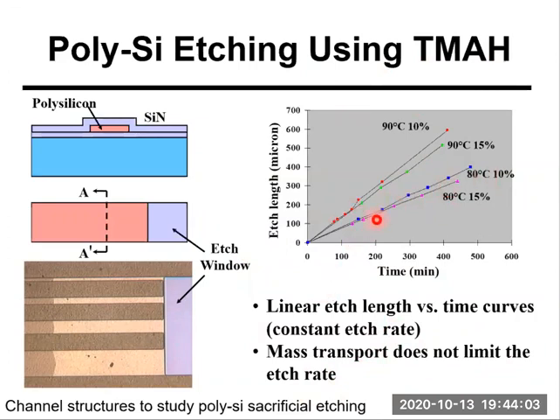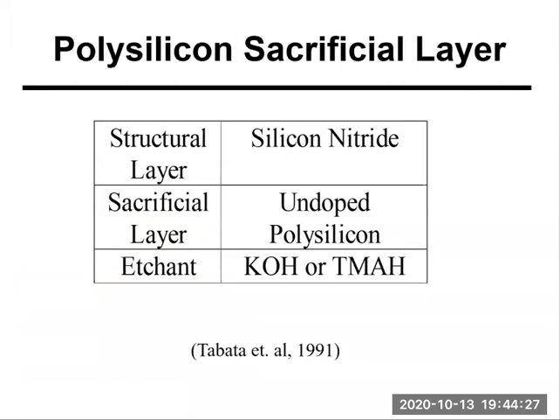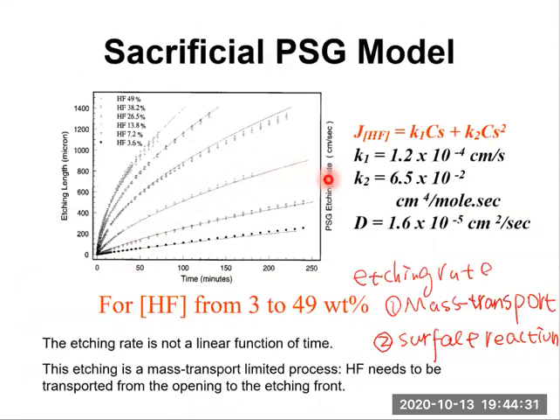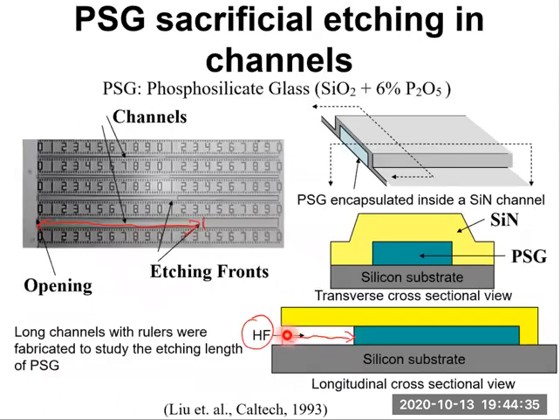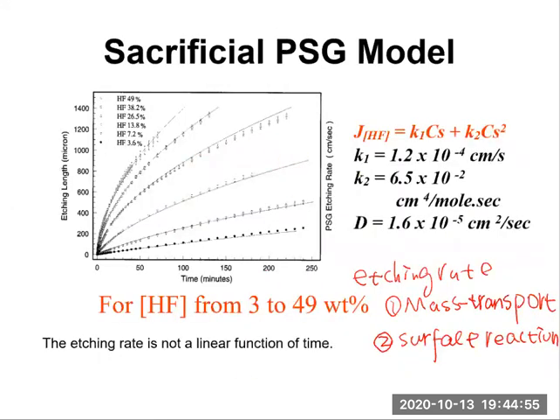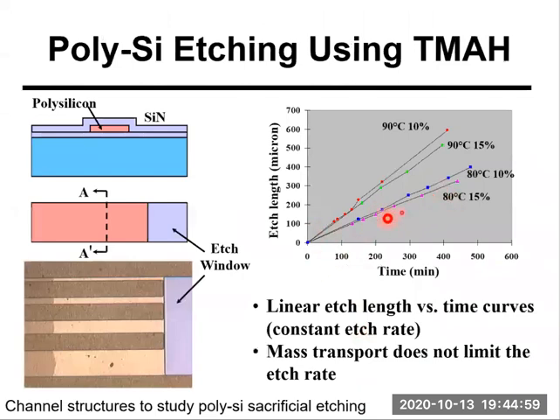But why is it linear? Well, this is what we observe, right? It's a linear curve. But why are these curves linear? Surface reaction, but that's what we observe. In the previous case, it was mass transport limited, because the etchant needs to be transported from the opening to the etching front, and the longer the length, the more difficult, or the slower, the transportation. So the etching rate decreases. That is very easy to understand. But why do we observe these linear curves?